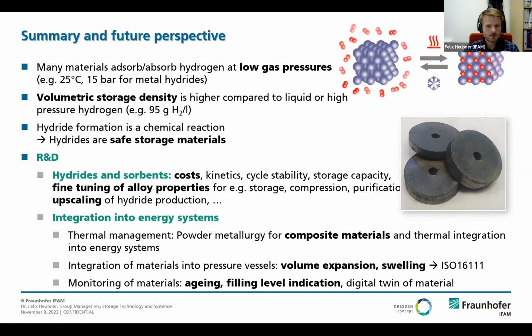Not only for storage, but again for compression, and there can be other applications like purification of hydrogen using metal hydrides, because this reaction of hydride formation is a selective reaction. So when you have a gas mixture of hydrogen, nitrogen, for example, you can use the sorbents to grab hydrogen out from the gas phase. And then we need fine-tuning of the alloys for the different fields of applications, for example, storage, compression, purification, and so on.